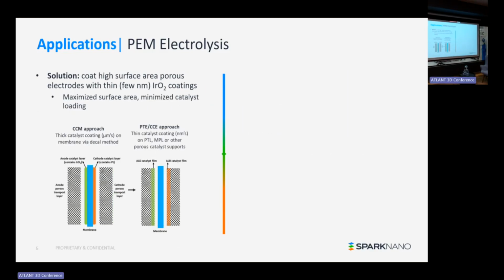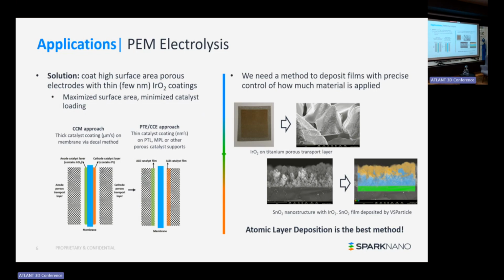One way to do that is by moving to a new concept of making a PEM electrolyzer, where the catalyst layer is not coated on the membrane, but instead you use a high surface area porous support, and then you deposit a very thin film, a few nanometers of iridium oxide. So you have a large electrochemical surface area, but because the film can be very thin, you can still reach very low loadings. This means, however, that you need a method to deposit these iridium oxide films with very precise control of how much material is applied, and also to do that inside porous substrates.